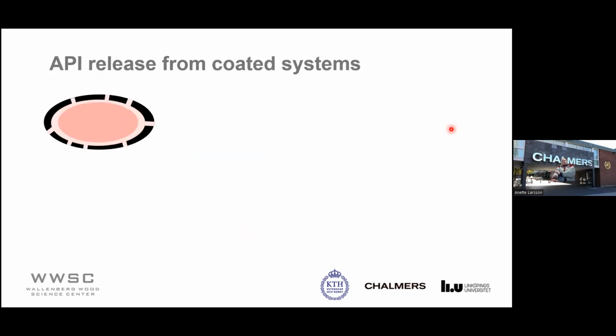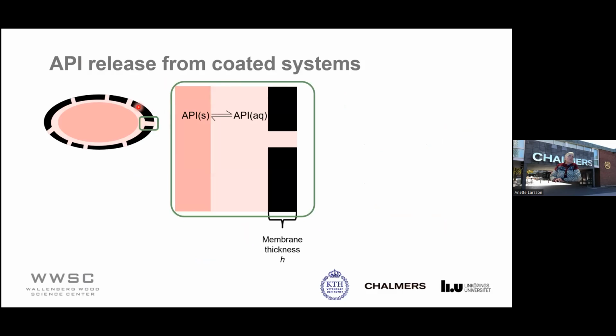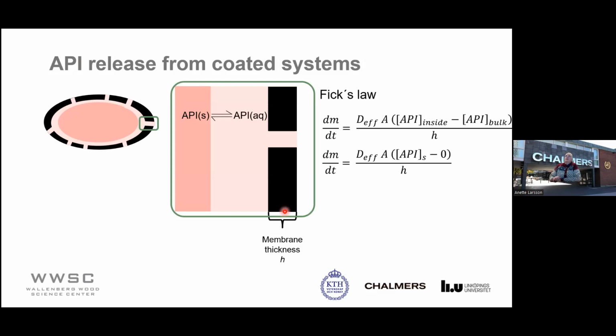So I would like to focus a little bit on these diffusion controlled systems, and I would like to zoom in here on one pore where we have the API in a solid phase and we have the API in a liquid phase, where it's dissolved, and here is the membrane. And we have this pore, and here is the surrounding bulk liquid. And the thickness of the membrane is H. And then we apply Fick's law to this one. So we take the concentration inside here, the membrane, minus the concentration outside in the bulk. And divided by the H, that will give us the concentration gradient.